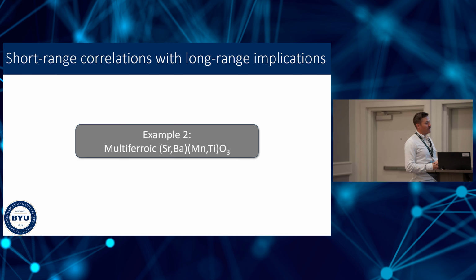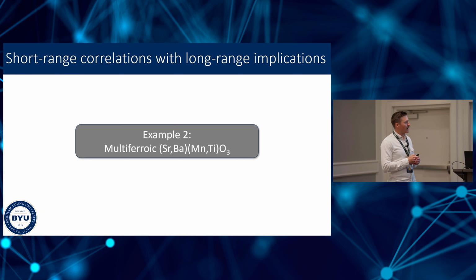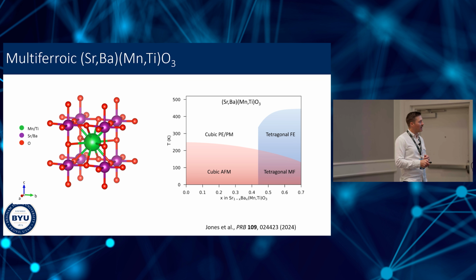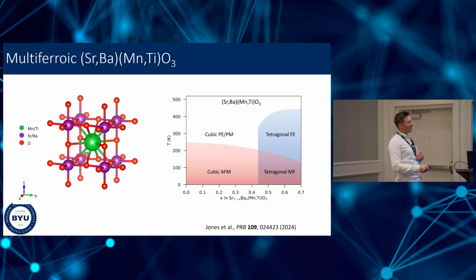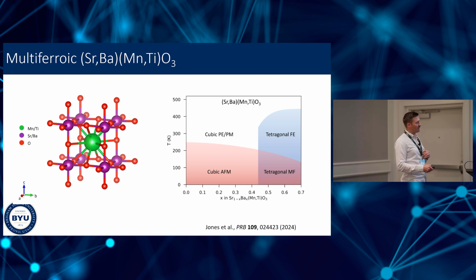We see similar behavior, but in a very different context: in strontium barium manganese titanium oxide, a multiferroic material. It has this pseudo-cubic perovskite structure. And if you put enough barium into the strontium site, then you can drive it from this cubic paraelectric structure into a tetragonal ferroelectric structure. All right? And it also develops antiferromagnetic order at low temperature. So this region right here represents a multiferroic state, where we've got ferroelectricity coexisting and, as we will see, interacting with the antiferromagnetic behavior.